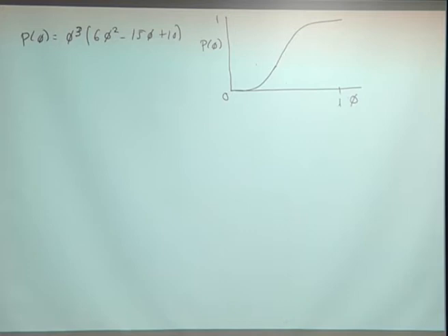Looks something like that. So p at 0 equals 0. P at 1 equals 1, which is what that really simple interpolation function I just showed you does. But this one has some very nice, very smooth characteristics associated with it at 0 and 1. And the fact that the derivative of p with respect to phi is equal to 0 at 0 and 1 is not an accident. That's chosen very specifically to make sure you get the right answers.